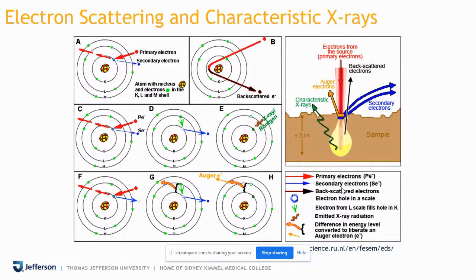As the method goes, in electron microscopy, as the name suggests, you incident a high voltage electron beam on the sample. As it shows on the screen, there is A and B, where A shows the primary electron beam hitting an atom. Now, I'm not talking from the perception of a nanoparticle, which is a big structure. I'm talking from the perception of the atomic. Now I'm going smaller. Think that you have a Fe3O4 atom which has a K electron shell, and you want to detect that this atom belongs to Fe and nothing else. So you have a nanoparticle which has Fe in it,